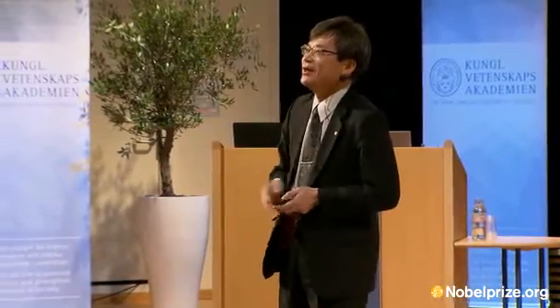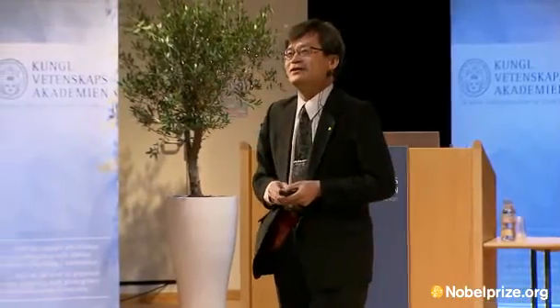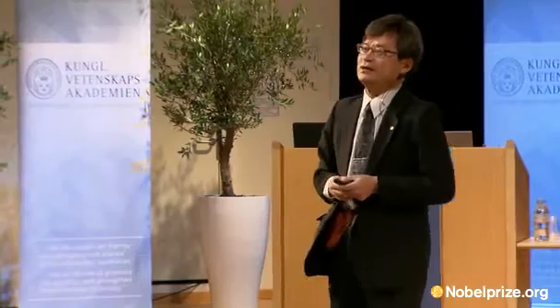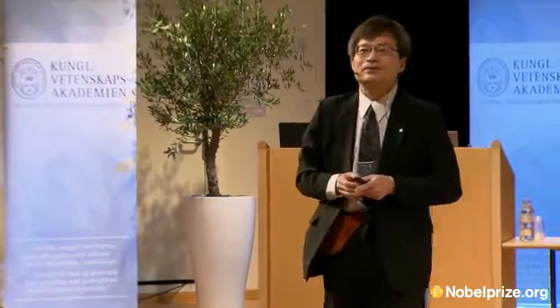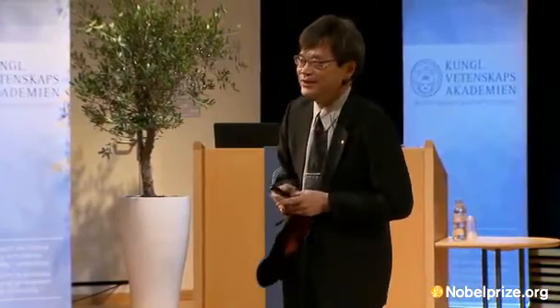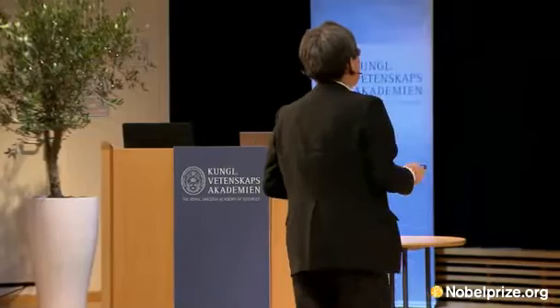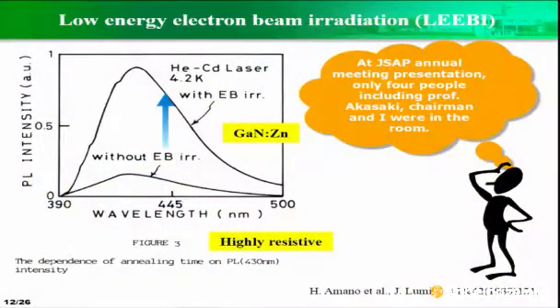At that time, the majority of the researchers were interested in zinc selenide or zinc sulfide. The researchers of the nitrides were quite a minority. Also, I observed the phenomenon that during the cathodoluminescence measurement of zinc-doped gallium nitride, the blue luminescence was irreversibly enhanced. So I called it the low-energy electron beam irradiation, LEEBI treatment for short. But even after the LEEBI treatment, the zinc-doped gallium nitride did not show the p-type conduction.